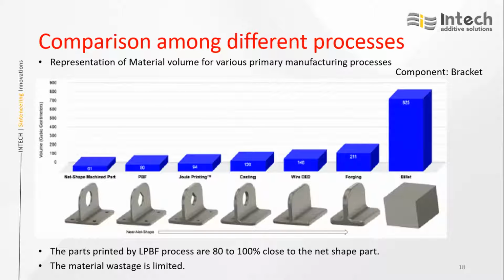If you see on the left hand side, to get that, first with the billet we required around 625 grams, whereas if you go for forging process it is 211 grams, wire DED 148, casting 120, joule printing 94, whereas in powder bed fusion process it is 80 grams.